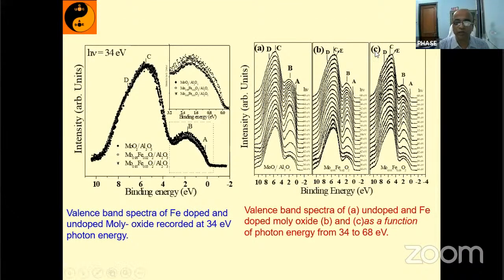So this is a lot of data one has to generate. You can see that this is one of the valence band spectra, at one energy, 34 eV, but then I used different energies and different spectra were generated. These are the three different samples. One is pure molybdenum oxide, one is 0.2% doping, and one is 0.5% iron doping. So one can generate these spectra, and then one can do the analysis.